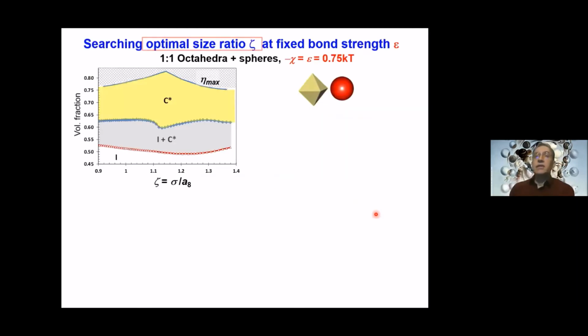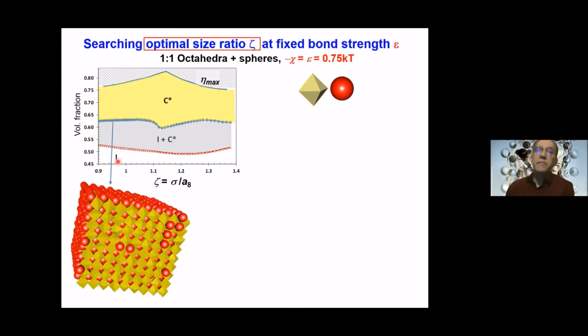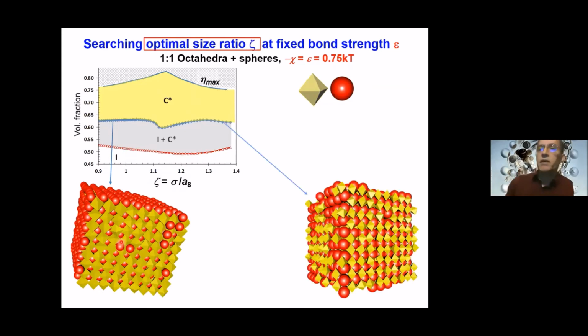To give an example for the same system I was telling you before, octahedra and spheres, these results are for the stoichiometric composition only, and for a fixed value of epsilon. So epsilon is 0.75 kT. This is a phase diagram showing the volume fraction as a function of zeta, the size ratio, diameter of a sphere over octahedral edge. The C star yellow region corresponds to the compound. The isotropic phase lives down here. This is the two-phase region. This corresponds to the C star phase for relatively small spheres. This corresponds to the case where the spheres are relatively large.